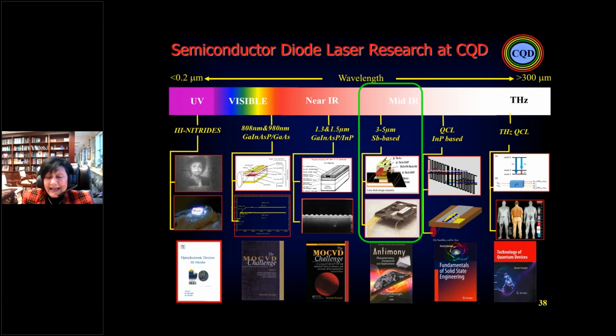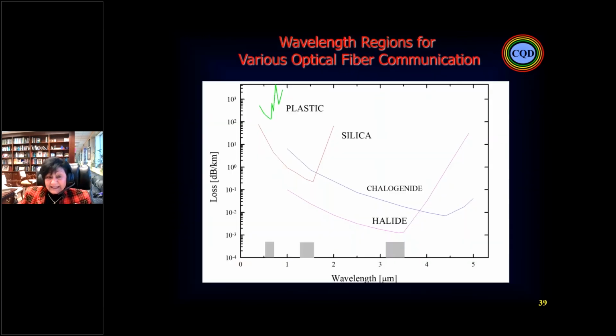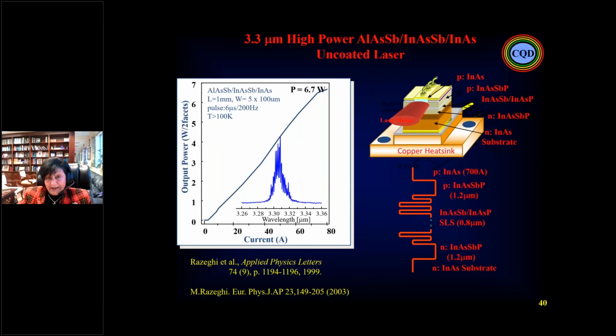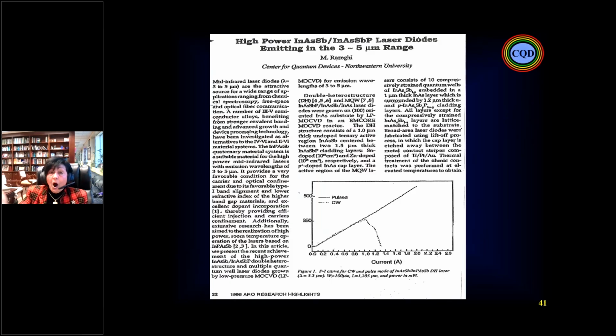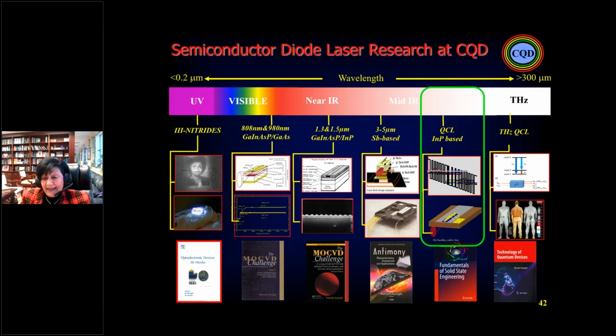I'm now going to the last part. It means that each laser, each wavelength, is important. So we came to the infrared 3.3 micron, and up to that they were using interband. That was the high power indium antimonide between 3 and 5 microns, a result published by the Army Research Office. But unfortunately, at this time it was intersubband, and the government, Durvasula and Henry Everett from the Air Force and from DARPA, came to ask me to be involved in the quantum cascade.